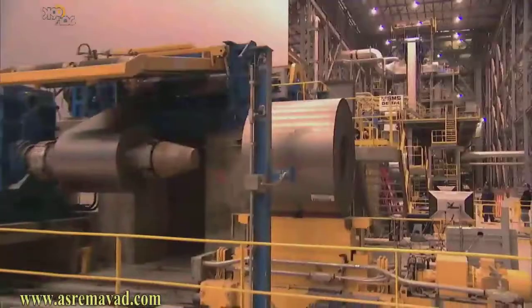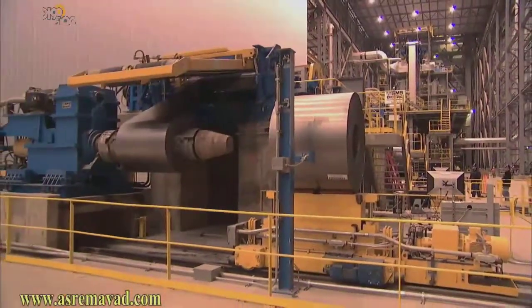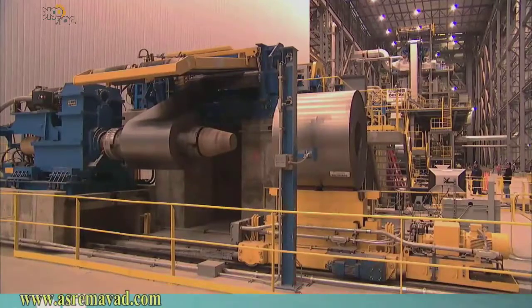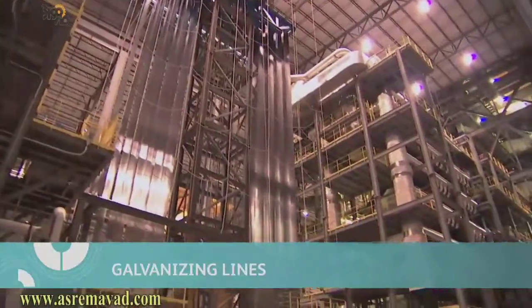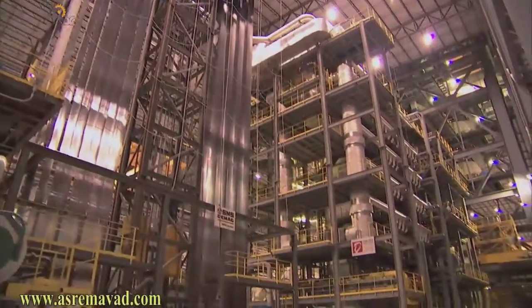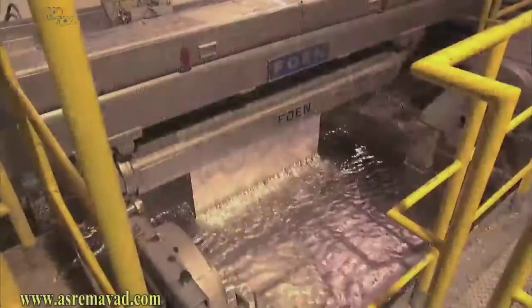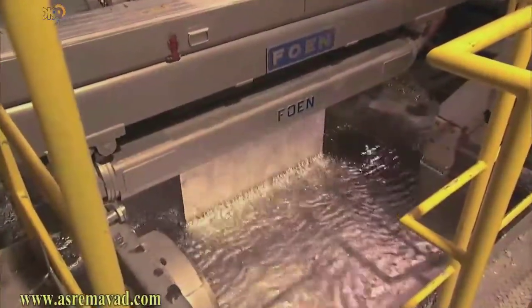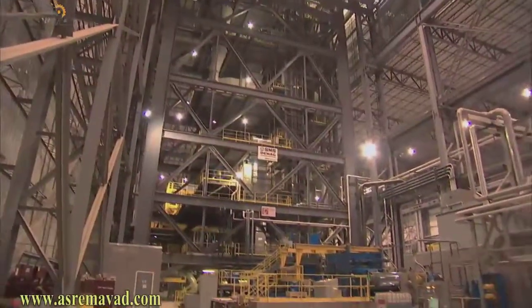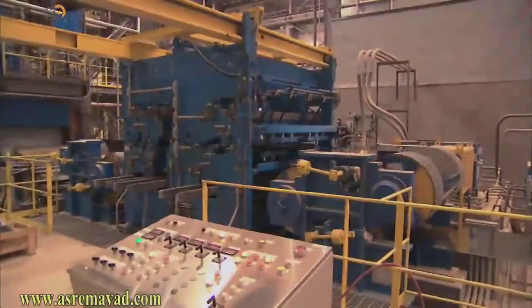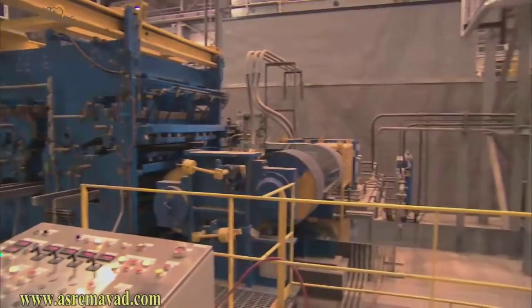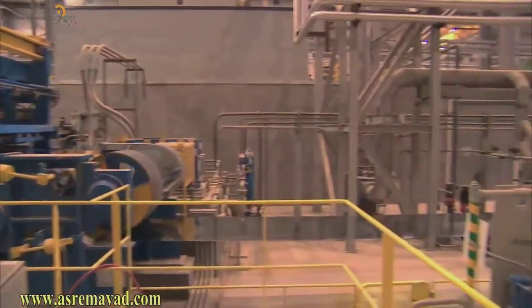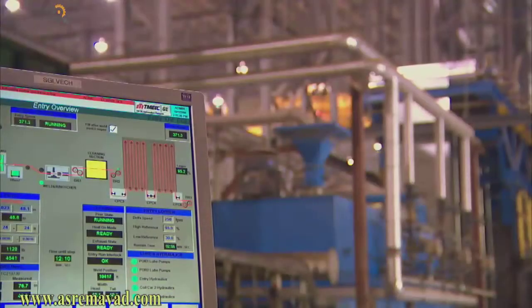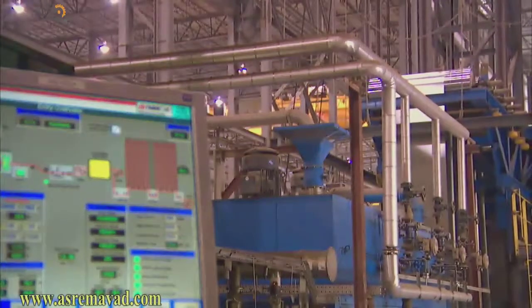For corrosion resistance, hot-rolled or cold-roll coils may have a coating of zinc applied at a continuous galvanizing line. The coils pass through a cleaning section, vertical annealing furnaces, and a molten zinc pot. Vertical ovens bake the zinc to the coil. Inline tempering and tension leveling ensure the best surface and shape. Rust inhibitors can be added at this stage if the product will not be painted.